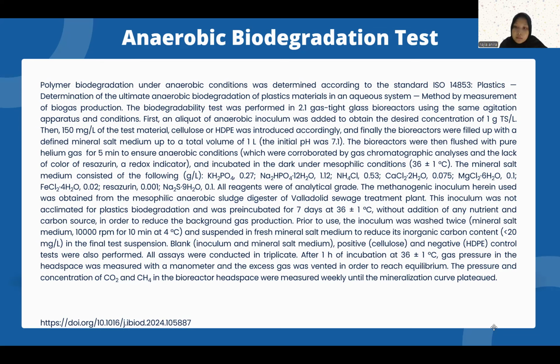The methanogenic inoculum used was obtained from the mesophilic anaerobic sludge digester of the Valladolid sewage treatment plant. This inoculum was not acclimated for plastic biodegradation and was pre-incubated for 7 days at 36 plus minus 1 degrees Celsius without addition of any nutrient and carbon source.